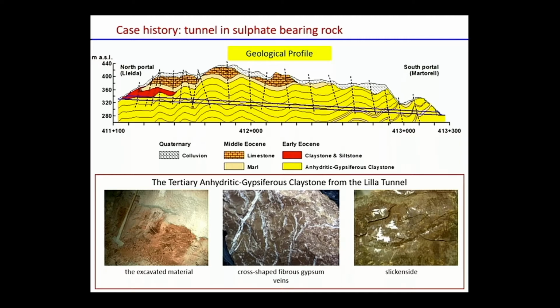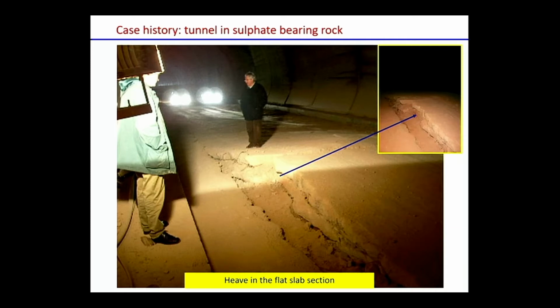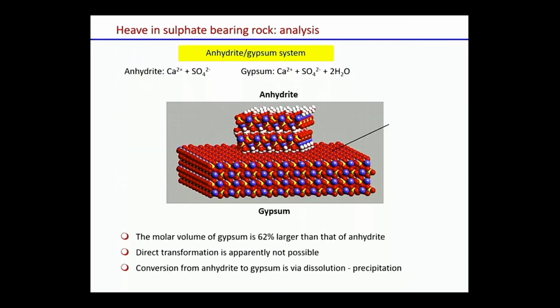So you have hydration of this material due to vapor migration. And what happens is that in these veins, there are some phenomena that we studied. One of the possible mechanisms is that these veins in fact contain anhydrite, and this anhydrite is hydrated by water and expands when it is transformed to gypsum. It was observed that we have a strong swelling of this material. So chemical reactions do not conserve volume. We have anhydrite; if you add two molecules of water, the molar volume of gypsum is higher, so we have expansion.